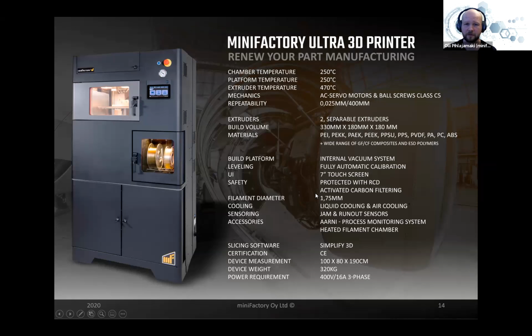Then the other thing is that we have a heated filament chamber in the system, so it ensures the optimal environment for materials during printing. Without this kind of controlled, heated material station, the printing quality would start to suffer in a critical way after a couple of hours, even though the material would be perfectly pre-dried in advance. But these materials absorb moisture quite easily, just like PA materials. So with this integrated feature, we can ensure high printing quality even in really long prints.